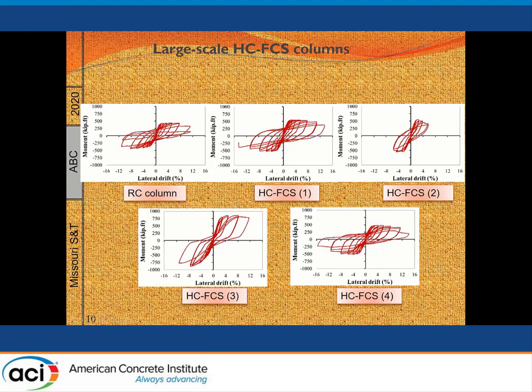The second one, the one in the top middle, also behaves very similar to the reinforced concrete one, but with a higher strength. The higher strength can be achieved by changing the tube thickness to reach the required moment. And then the one far right is one of the specimens where we use a very thin FRP tube. Because we just changed the FRP tube, we achieve the same strength as the one in the middle, but it was very brittle because we do not have enough confinement.